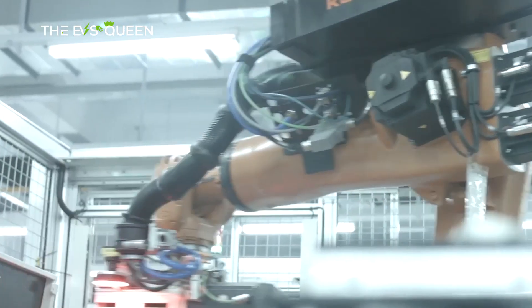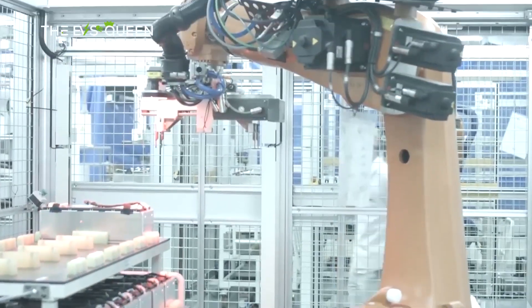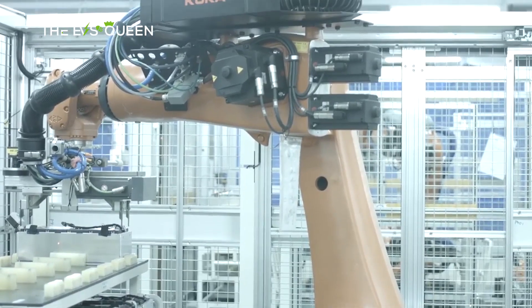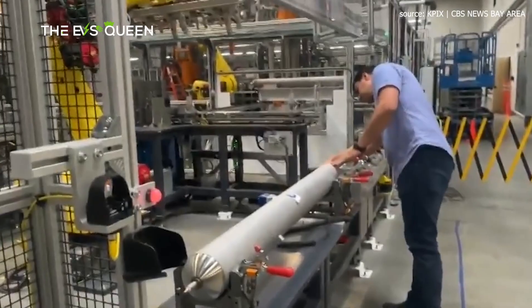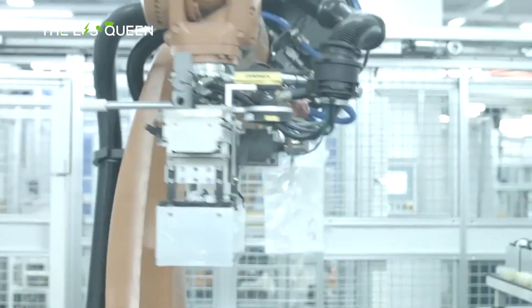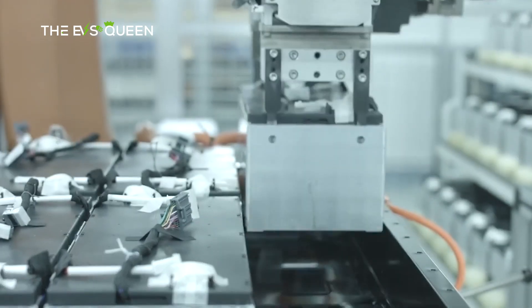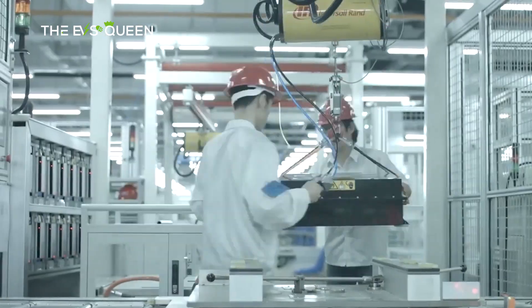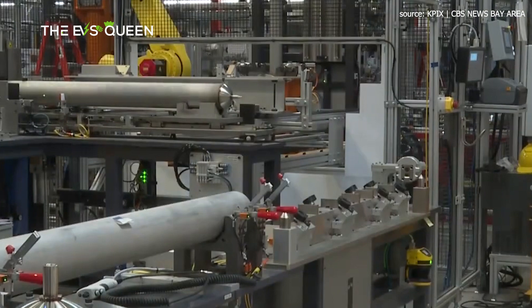Cost-wise, the manufacture of nickel-hydrogen batteries is currently more expensive than lithium-ion ones. Additionally, the energy storage density of lithium-ion is the best we have achieved to date, meaning a larger number of nickel-hydrogen batteries would be required to get the same output as Li-ion. Where nickel-hydrogen handsomely beats lithium-ion is the 30,000 charge cycles, which ensure the battery can last up to 30 years. The company estimates that the batteries will retain 86% capacity after these cycles, too.